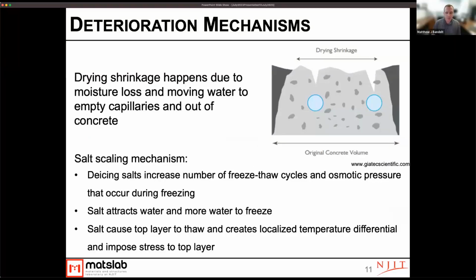And all of these durability issues are in one form or another due to some sort of deterioration mechanism. So if we think about drying shrinkage, for example, that happens due to moisture loss and moving water in and out of concrete. Salt scaling mechanisms are somewhat similar in the sense that de-icing salts increase the number of freeze-thaw cycles, which causes pressure to build up and local cracking and delaminations that can occur.